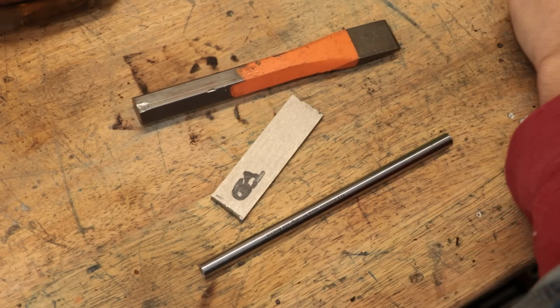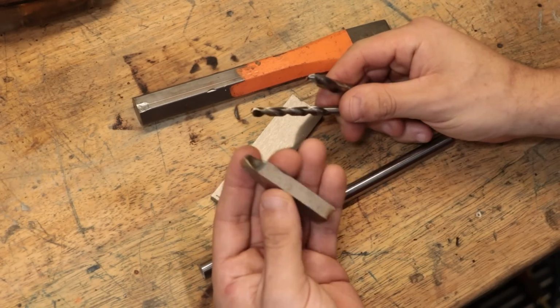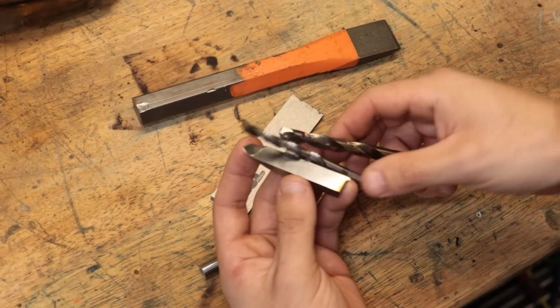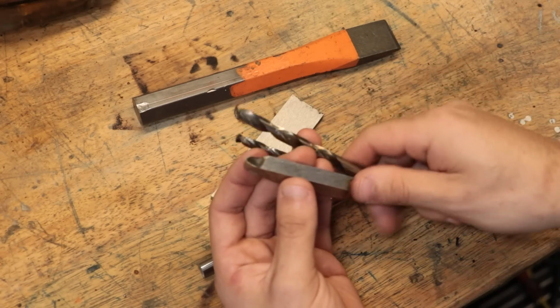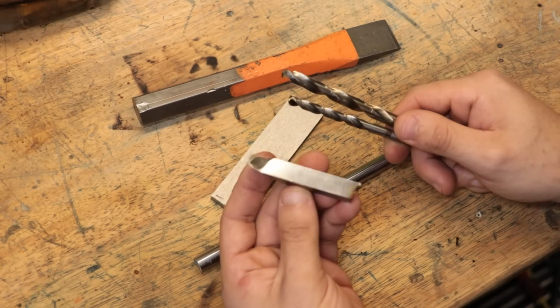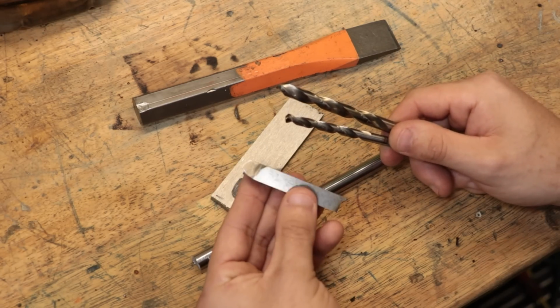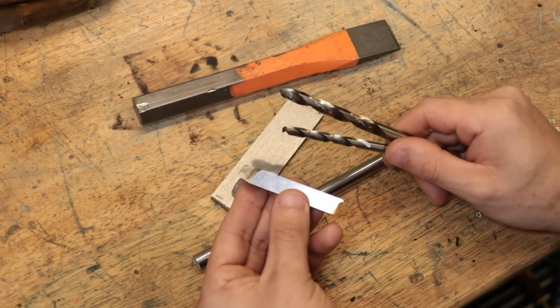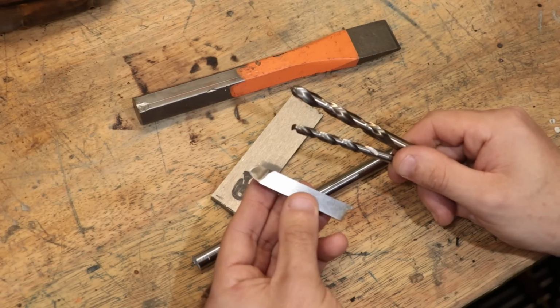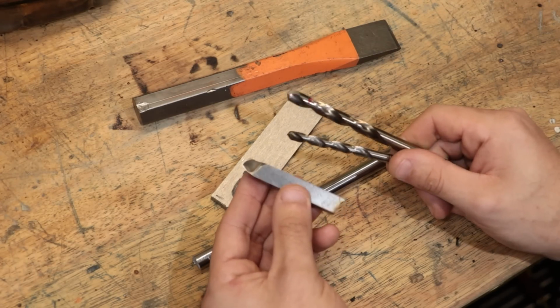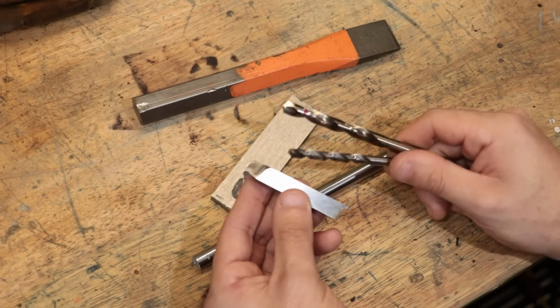High-speed steel is also no different. It wants a minute or so at 1300 degrees Celsius, and that probably explains why I could never get it properly hardened in my workshop. And managing that critical temperature is not that easy with my setup. And as a result, I could never get it past, say, 50 or 55 Rockwell C hardness, when what I was really aiming for was 65 plus.